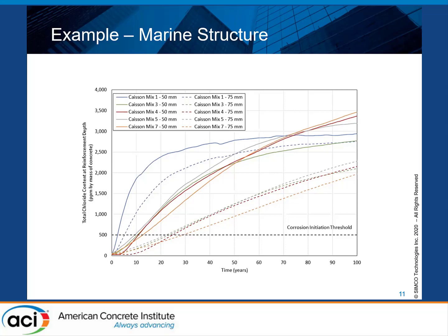And I decided the threshold would be at 500 ppm. It's not a strict calculation based on the cement content, but it's in the range of values that we get usually. And you can see that even if the threshold varies, it doesn't get us to 50 years. So that brings us to the definition of service life. On this graph, it shows time to corrosion initiation. If you need a service life that includes a propagation phase, then you may add a few years, but it's not